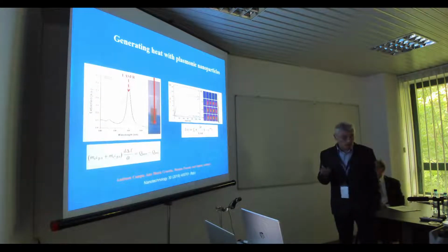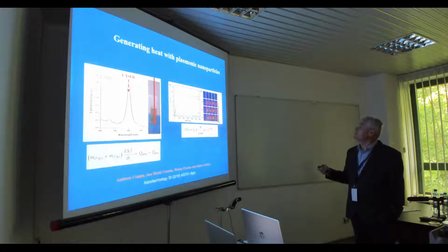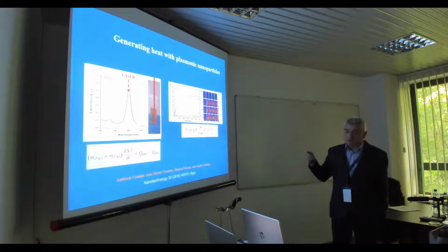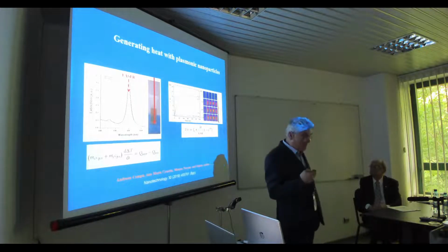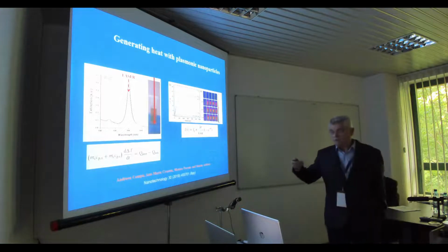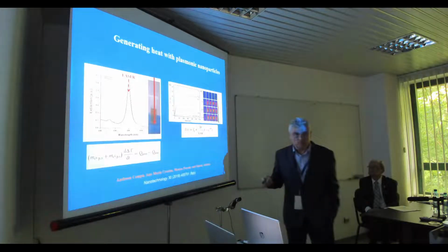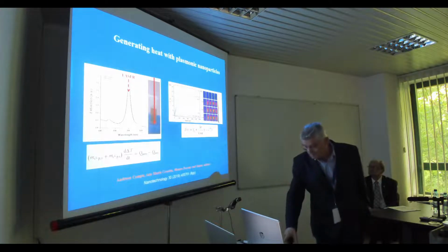What is the conclusion here? Then you can increase the temperature only by maximum 20 degrees or even 10-20 degrees, but this is enough starting from the physiological temperature of 37, so with 10 degrees it's enough to induce apoptosis in the cells. And you can repeat this experiment.